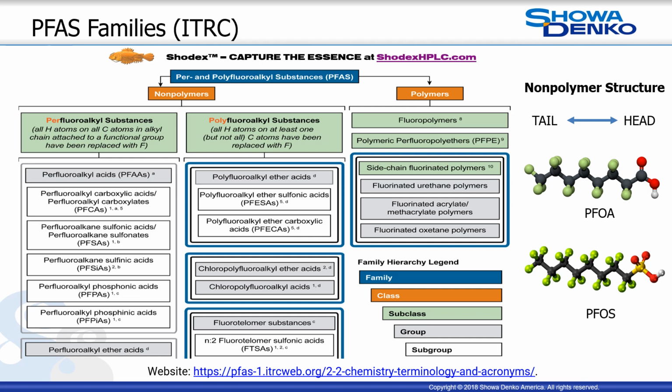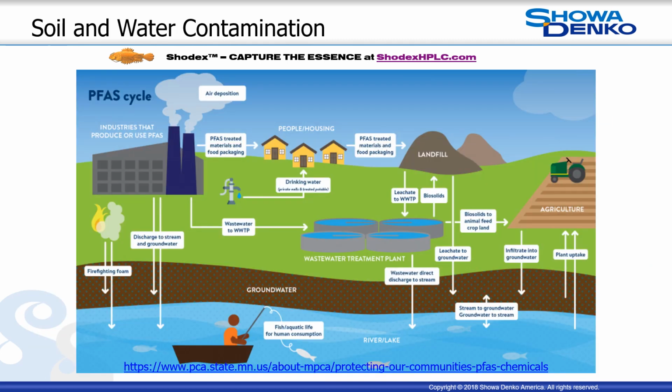The CF bond is one of the strongest covalent bonds in chemistry. Thus, PFAS are not prone to dissociation and release of the fluorine atom under normal environmental conditions. Further, the carboxylate or sulfonate end groups allow for bioabsorption, leading to many possible negative health outcomes. PFAS are stable under environmental conditions, and many PFAS, especially C1 to C10 chain length compounds, remain in the soil and can quickly migrate into groundwater and eventually to the drinking water supply.